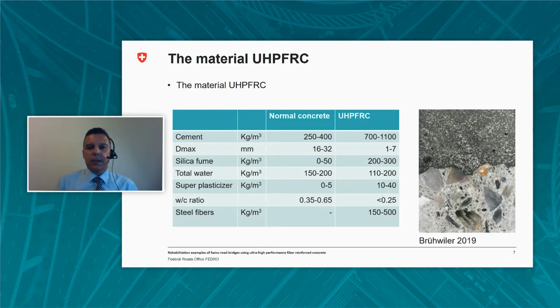Now, the cement content is more than 2 times higher than for a normal concrete. For instance, for an ordinary concrete, the cement content is between 250 to 400 kilograms per cubic meter, whereas for the ultra-high performance fiber reinforced concrete, the cement content is 700 to 1,100 kilograms per cubic meter.